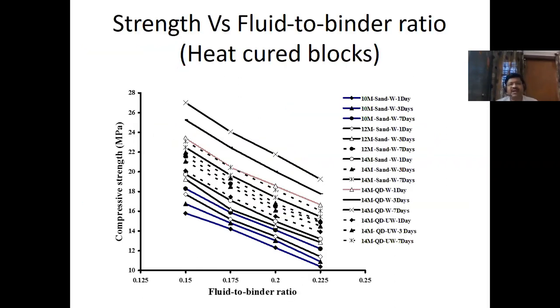Now, this is the result of heat cured geopolymer blocks. On the x-axis is the fluid binder ratio, and on the y-axis is compressive strength. It ranges from 0.15 to 0.225. As the water cement ratio or fluid binder ratio increases, strength decreases. Below 0.15, we could not make mortar at all because it is not possible. Beyond 0.225, we cannot compress because it becomes saturated. So that's why this is in the range of 0.15 to 0.225. Sometimes it will go up to 0.3.